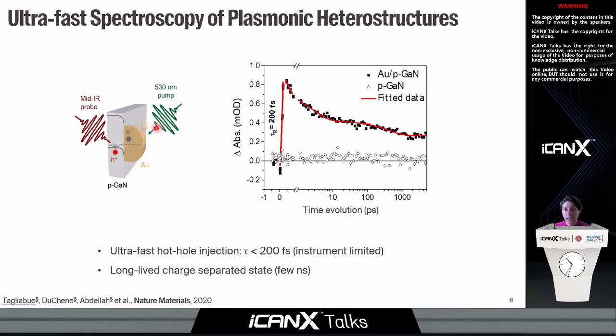We use a green light pump, and then we use a mid-IR probe to measure the population of holes in the semiconductor. What this transient plot shows you is that very quickly we have a strong rise in the absorption signal from the mid-IR probe. And this rise time is limited by the instrument at 200 femtoseconds, telling us that hot holes inject across the interface at a time which is shorter than this, which is totally comparable to the injection time of hot electrons that had been measured before.